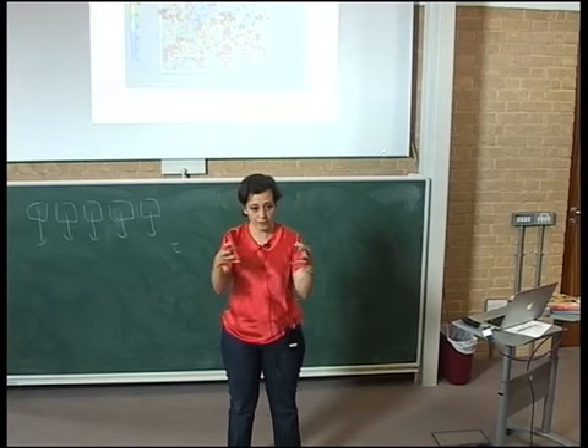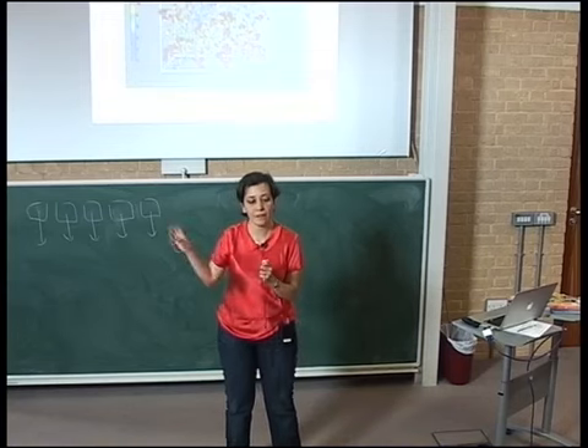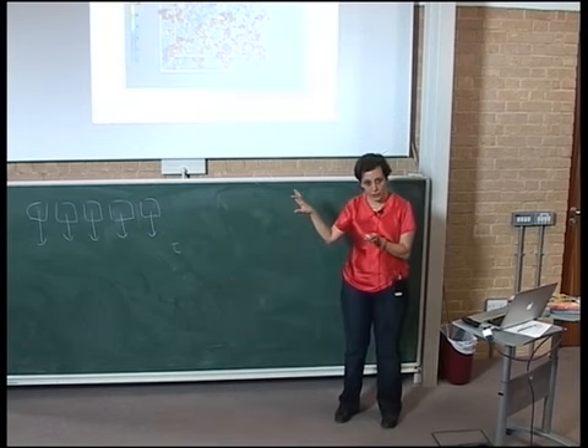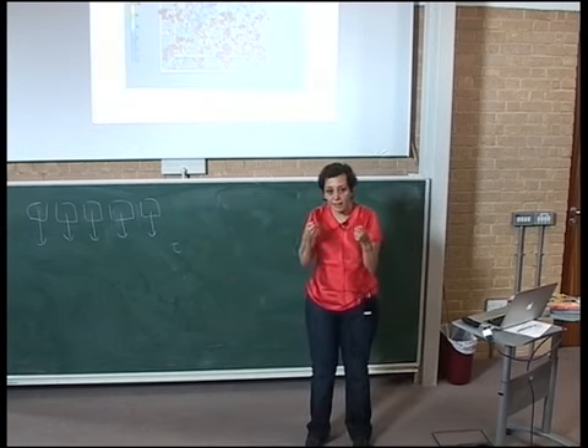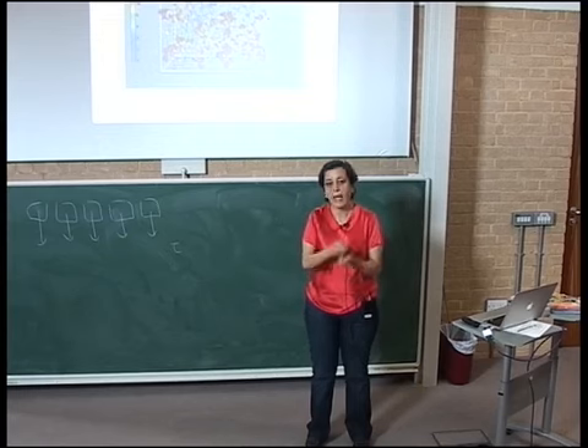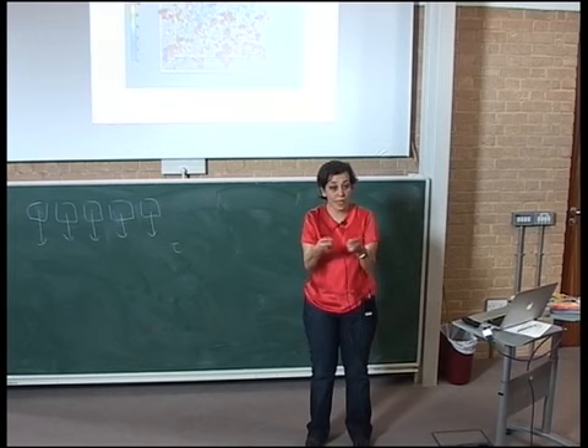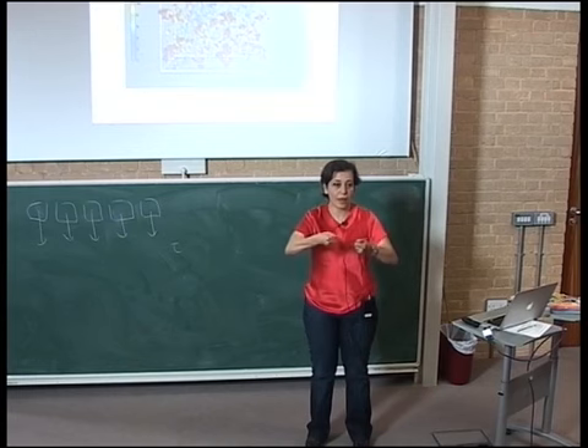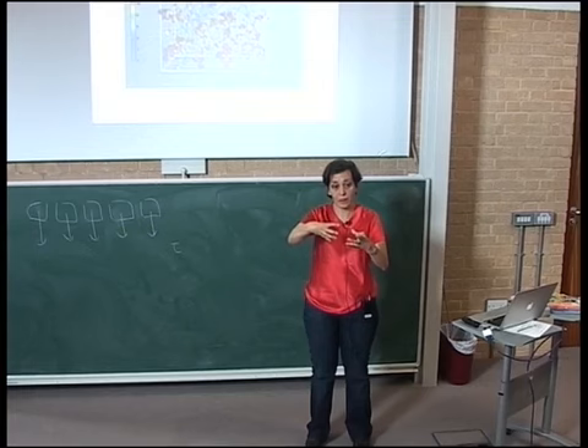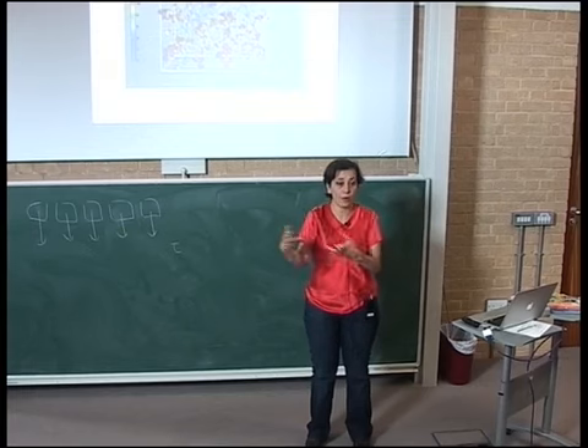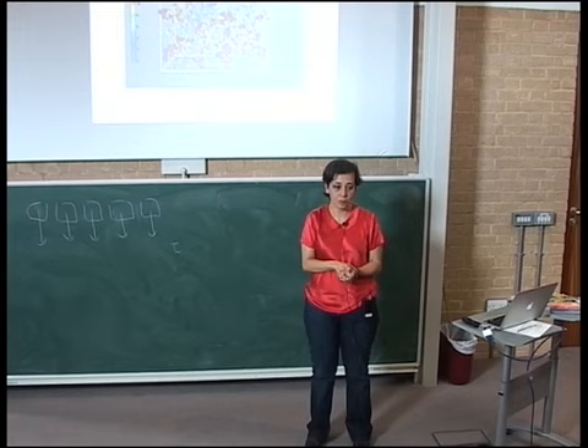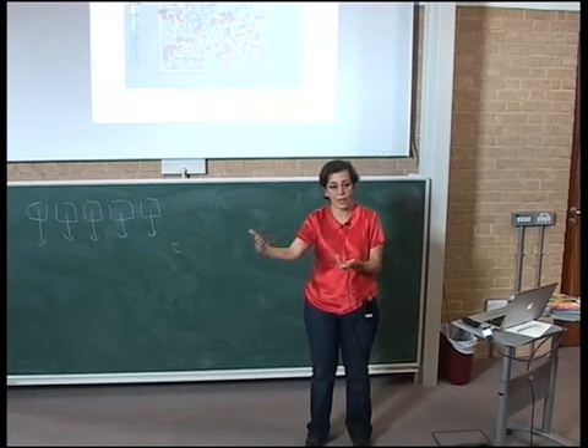Well, one thing that you can see is that if you compute local stresses in the structure, these regions are the regions where tensile stresses tend to concentrate. And yes, I agree, this is related to the fact that you have more bonds, and so this environment is under stress more than the other environments. But what I wanted to say is that it's not that I'm just counting more breaking events because there are more bonds.